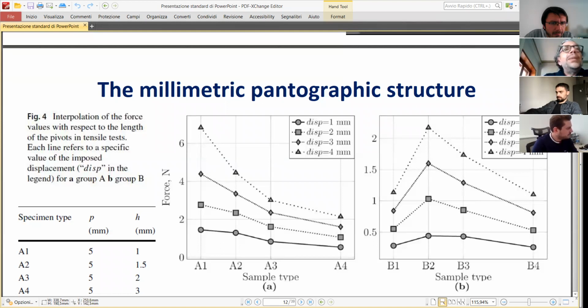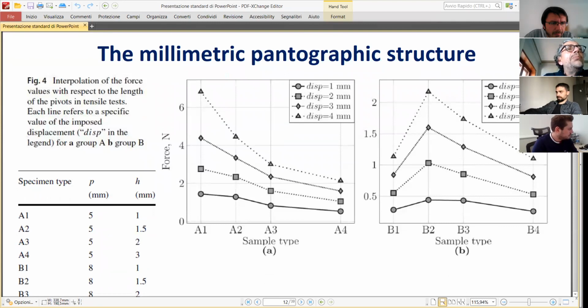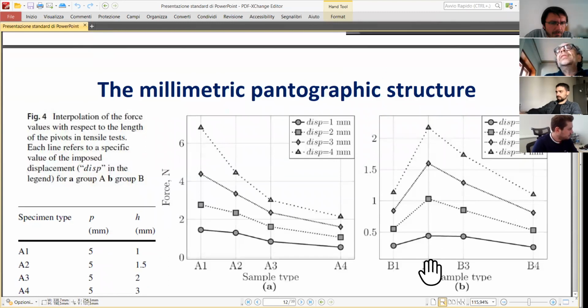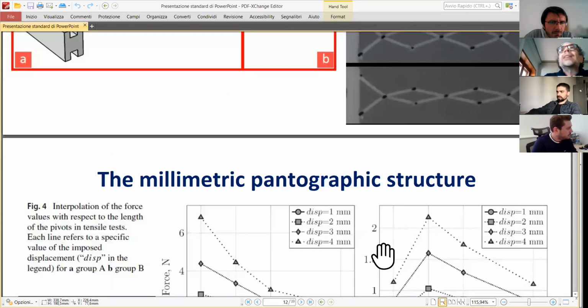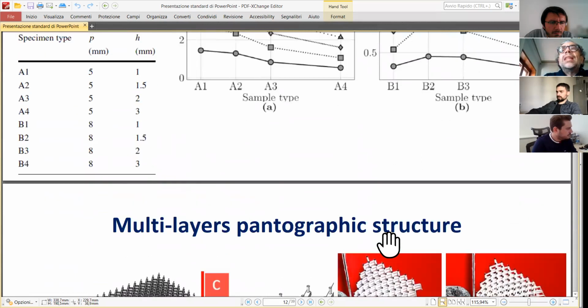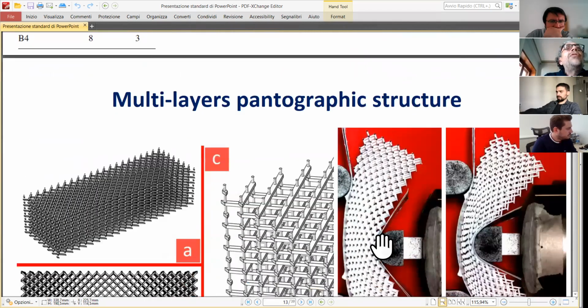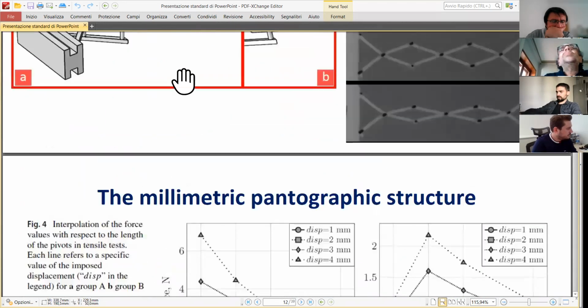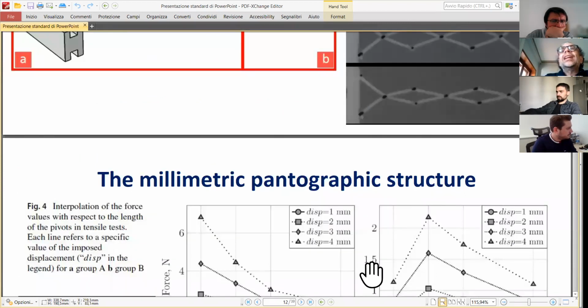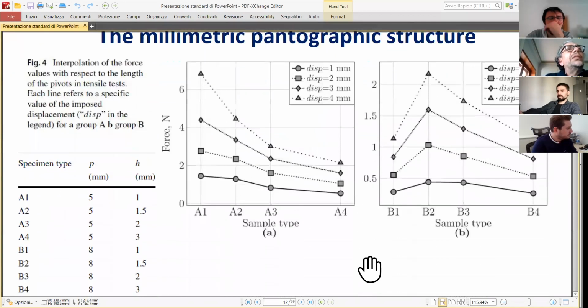specimens, so with specimens having this B2 dimension, you get a maximum of the exerted force. And you can range from 0.25 up to 2.25, simply changing the parameters characterizing the microstructure. So what it means is that with a very small change of volume, so changing a little bit the diameter of these pivots, you can get a macrostructure whose mechanical behavior is dramatically different.